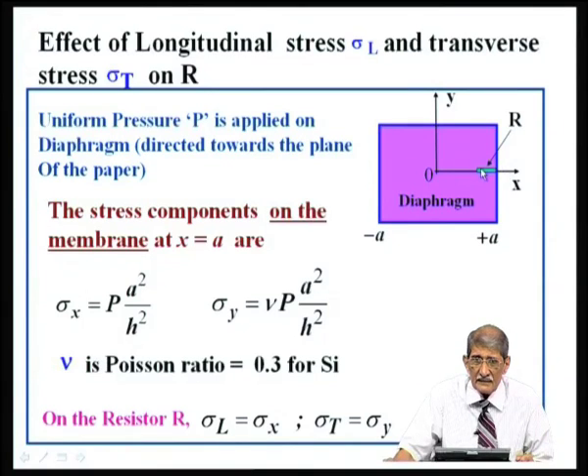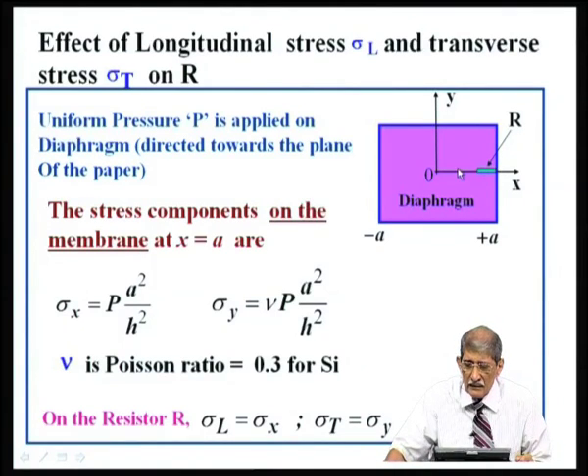Okay. If I put a resistor there in that direction, perpendicular to the edge of the membrane, that will be the longitudinal stress that we are talking about. Stress in x direction is along the direction of the resistor where the current flows, that is longitudinal. So, sigma x for a pressure P will depend upon the ratio of the membrane dimension. For example, if I take a square membrane of side 2A, if I take 0 at the center of the membrane, this is plus A and the other edge is minus A. So, if 0 is at the center, the stress near this edge of the membrane is applied pressure multiplied by A divided by thickness H, whole square. H is the thickness of the membrane.